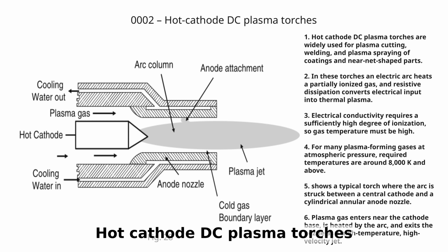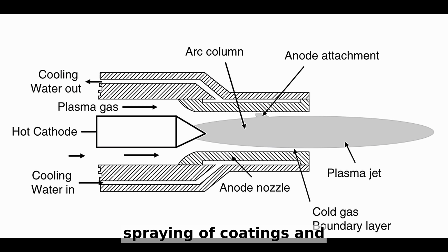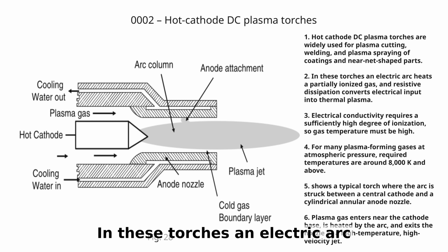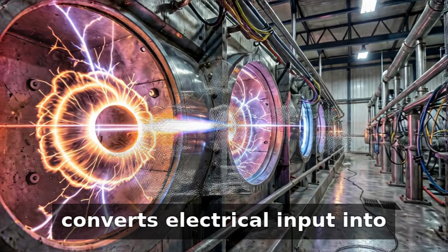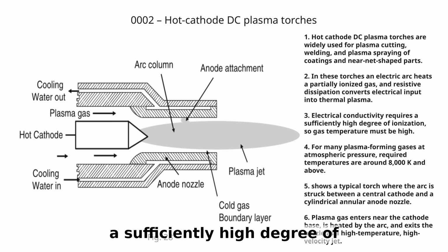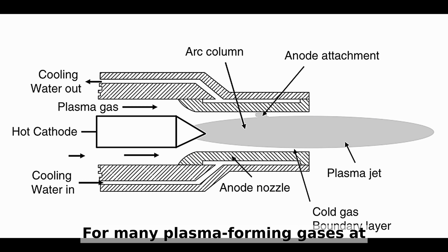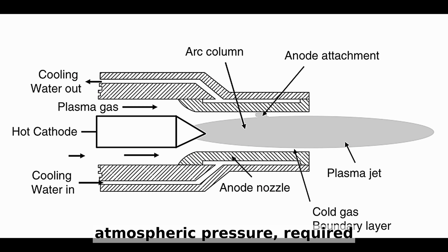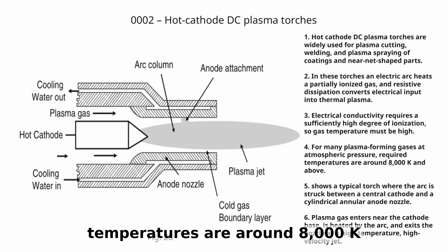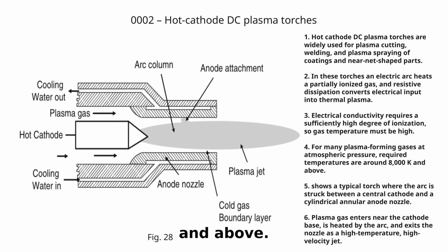Hot cathode plasma torches are widely used for plasma cutting, welding, and plasma spraying of coatings and near-net-shaped parts. In these torches, an electric arc heats a partially ionized gas, and resistive dissipation converts electrical input into thermal plasma. Electrical conductivity requires a sufficiently high degree of ionization, so gas temperature must be high. For many plasma-forming gases at atmospheric pressure, required temperatures are around 8,000 Kelvin and above.